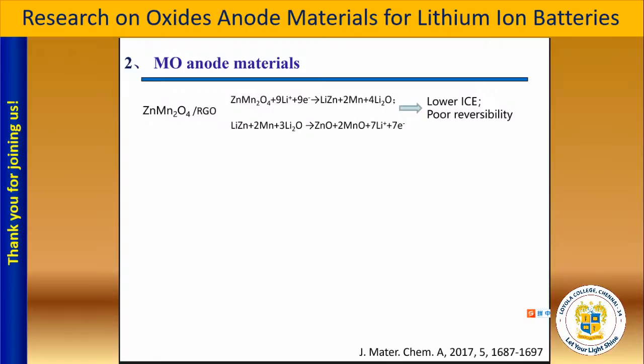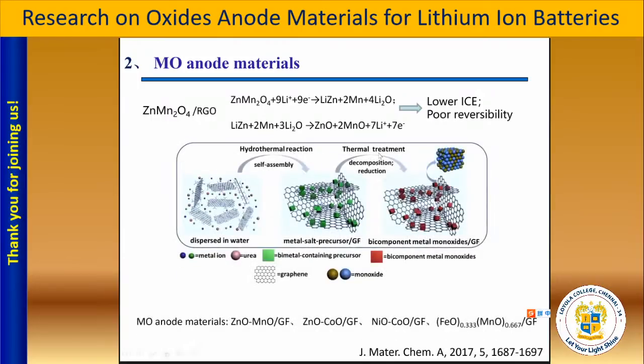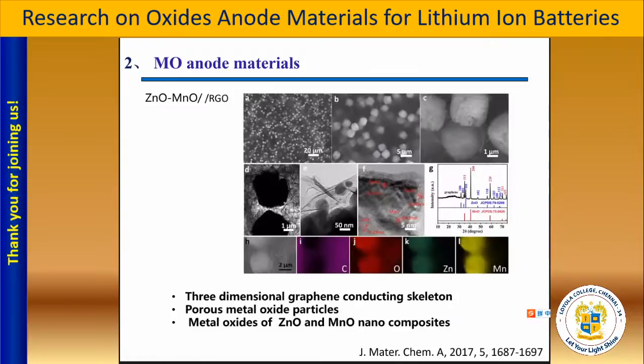The second is about some oxides. We use hydrothermal reaction and thermal treatment to get kinds of oxides, such as double metal oxides, or two kinds of oxides with different kinds of carbon, to make composites for the anode material application. From this research, we get the result that graphene is very important for forming the conducting skeleton. And when we adjust the technology, we can get oxide particles with kinds of porous structures,